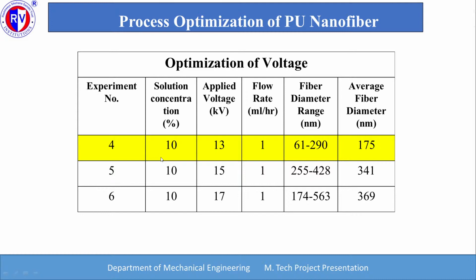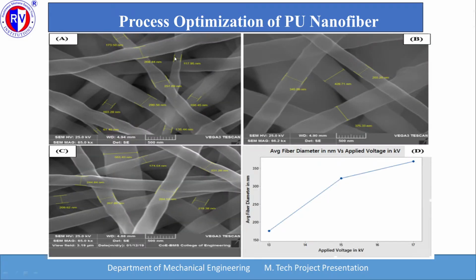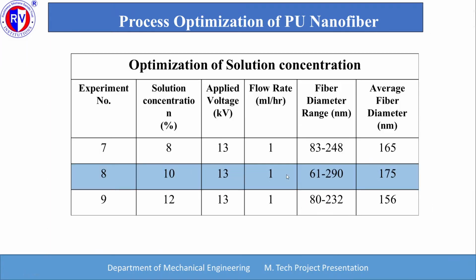Second, the optimization of voltage. In this set of experiments, solution concentration and flow rate are kept constant, and the applied voltage is changed from 13, 15 to 17. In this, we have got the minimum diameter at 13 applied voltage. These are the same SEM images that we have got.